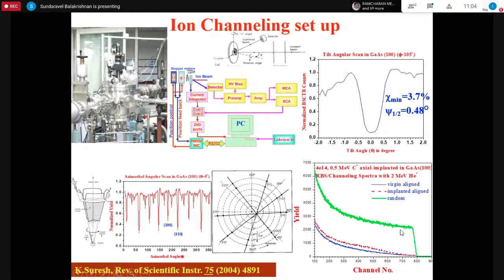In this one, we take a small energy window on this high energy side, and in that window, how much is the total counts? That count for a fixed charge we find for a specific angle. Angle theta is kept at 5 degrees, and from gallium arsenide as such, we cannot resolve the gallium and arsenic masses, so it looks like a single error function set of thing.